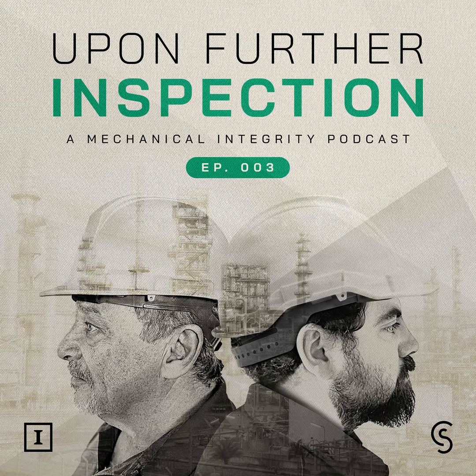So there was a lot of metallurgical lab work being done on taking cutout samples of suspected SSC and then doing Vickers microhardness testing across the thickness of the fracture area to look at where the hardnesses went. Typically you're looking at a Brinell hardness, or Vickers hardness, of less than 200 to be okay. If it was 200 or above, it was too brittle. But then that's where we got into understanding the importance of post-weld heat treatment on any welding that was done on this equipment.